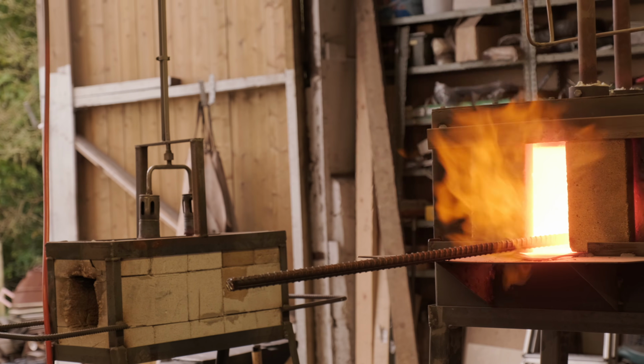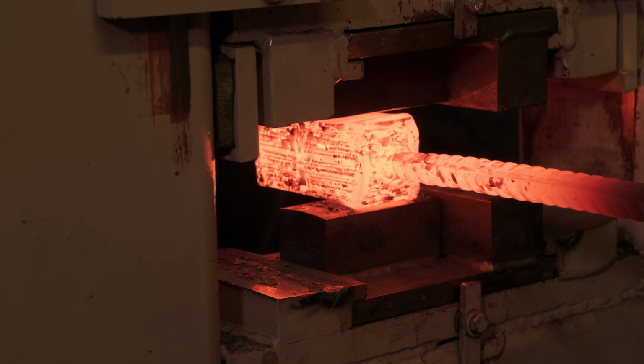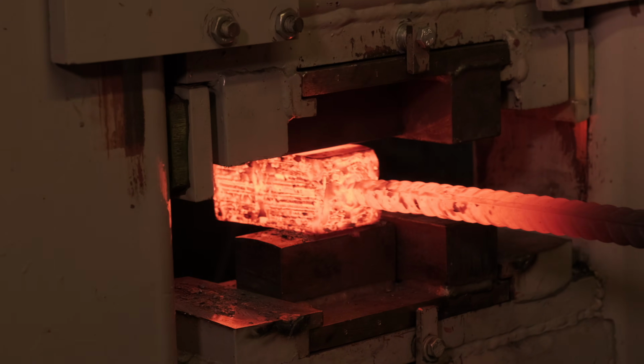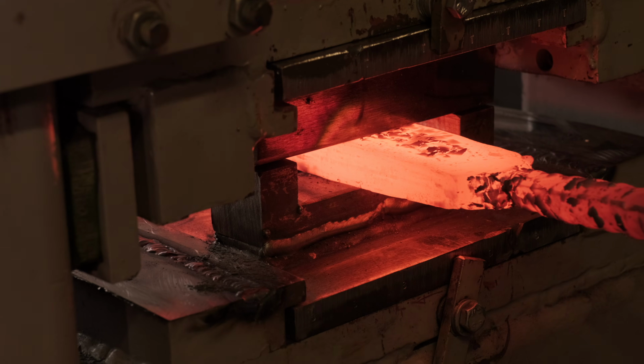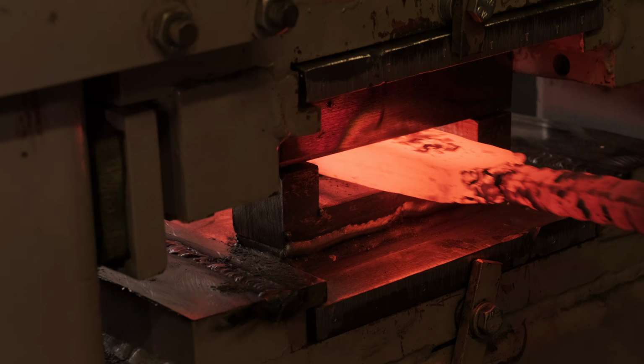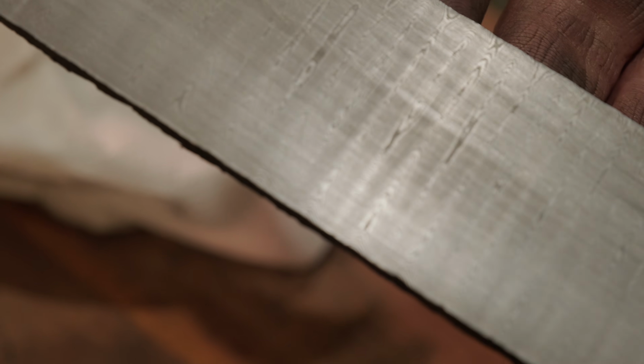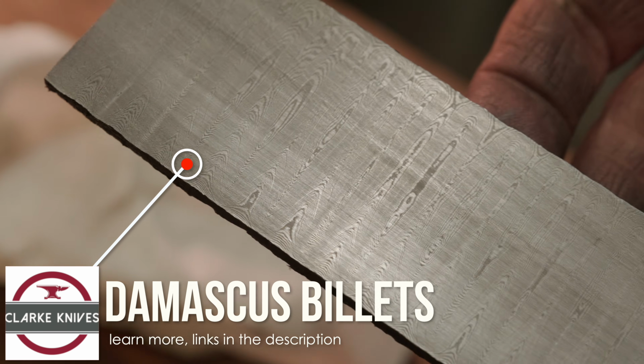together. Because what we're doing by forge welding is we're getting up to a high enough temperature and pressing those surfaces close enough together that the crystals of iron within the layers start to grow across the boundary. So where you've got two pieces of metal sitting together, like so, and we're putting pressure against them, the layers of steel are made up of crystals, and we want the crystals to grow across that boundary. When they grow across that boundary, the two pieces become one, or 30 pieces become one, depending how many layers